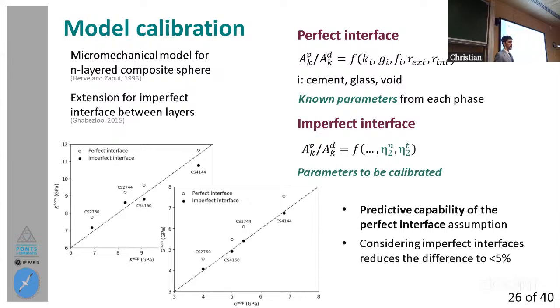With this, I show you here, in this first figure, the results of K, experimental on the x-axis and model on the vertical axis. And here the shear modulus G results, experimental on the horizontal axis, and vertical is the model results. If we have a value that coincides completely with the diagonal, then we have a perfect agreement between model and experimental parts. First, I show you there the white points, which are the results before considering the imperfect interface, meaning the perfect interface without any calibration at all.